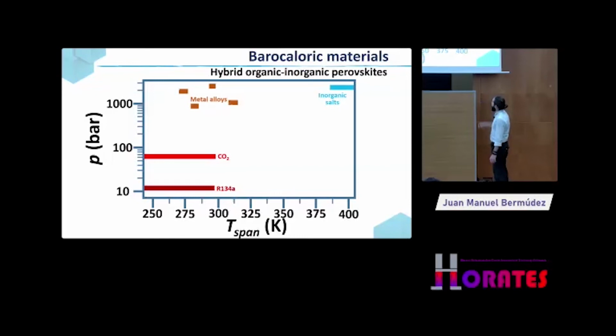The inorganic salts were a bit larger, but they operate quite above room temperature, so you cannot use them for ambient applications. And in the case of hybrid organic and inorganic materials, since we were applying small pressures, the operating temperature change was also very small. In this case, we could reach temperatures near room temperature, somewhere like 330 Kelvin, but other hybrid materials were far away from this ambient temperature.